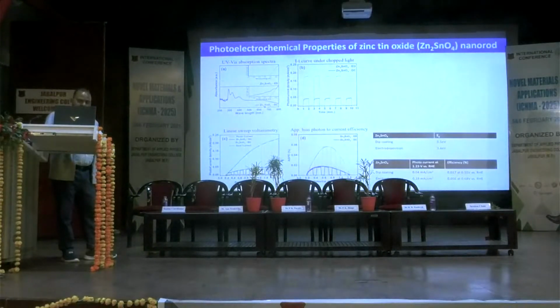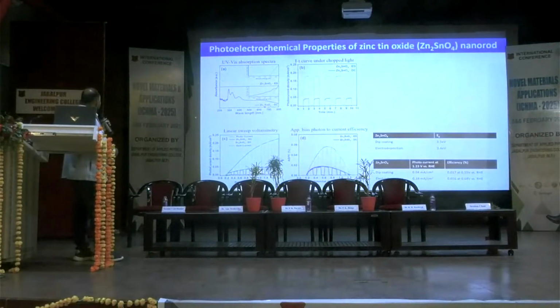Then this was the interesting figure when we investigated their absorption profile. That's very different, because their morphology is playing a very critical role. When we tested the electrochemical performance, you can see the current versus time profile plot when we chop the light on and off. So there is a very clear-cut difference between these two systems. The electrodeposition system shows far better performance. Even the efficiency is very high as compared to the other two systems.